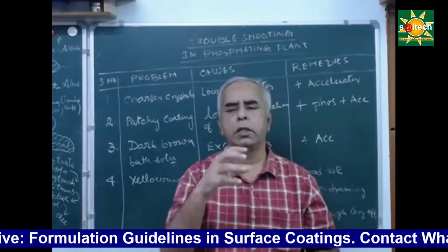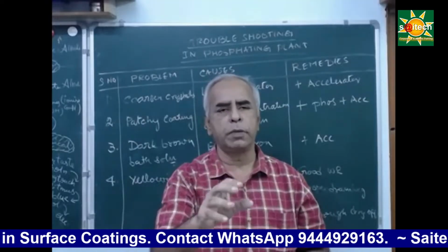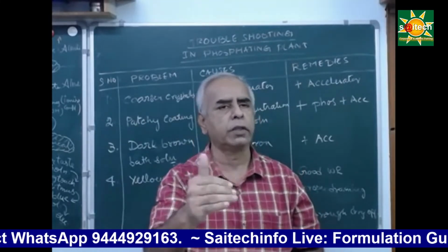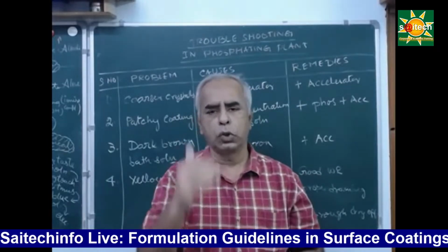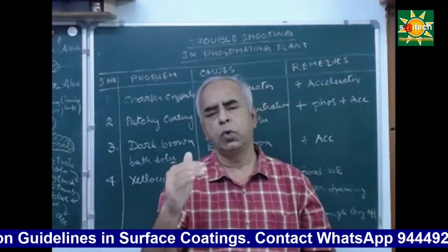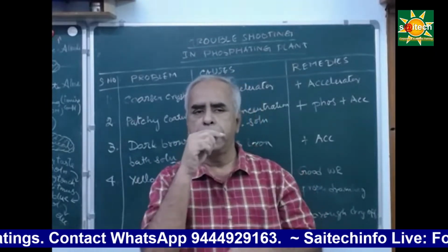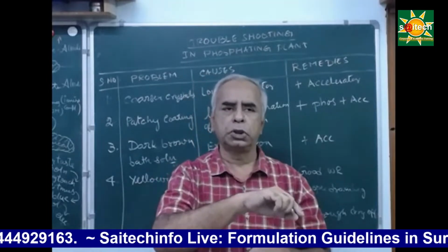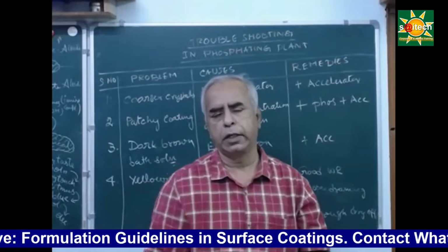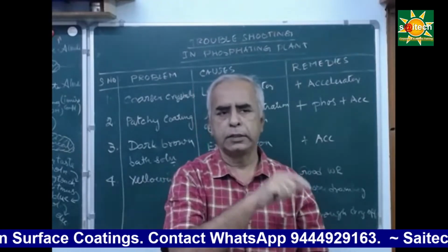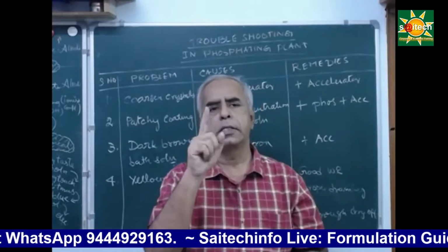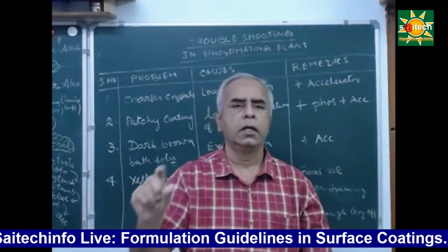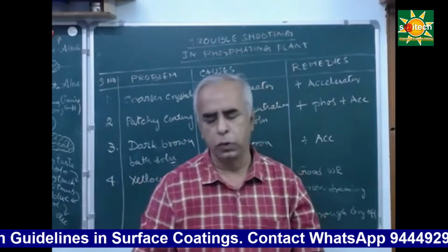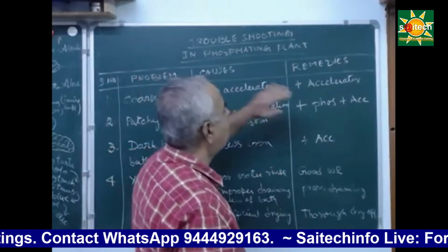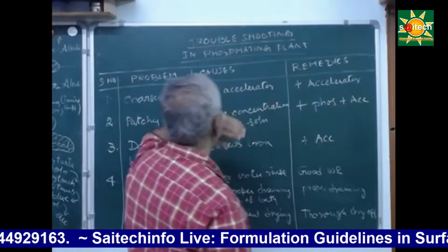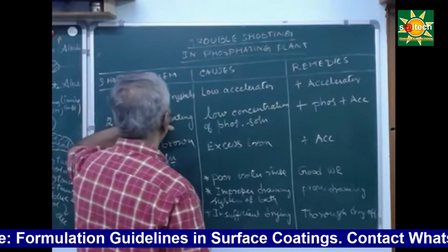So the best way is you have to keep the nitrite separate. There is a difference between nitrite and nitrate. Please make a note of it. Nitrite is NaNO2. Nitrate is NaNO3. That is nitrate. So nitrate can be added in the bulk of the solution already when you manufacture this phosphating chemical. But nitrite you should not add along with that system. That should be ideally separately supplied as an accelerator, or some people call it toner also. Okay, right. So you have to add carefully the accelerator if you feel that the phosphate crystals are coarser.